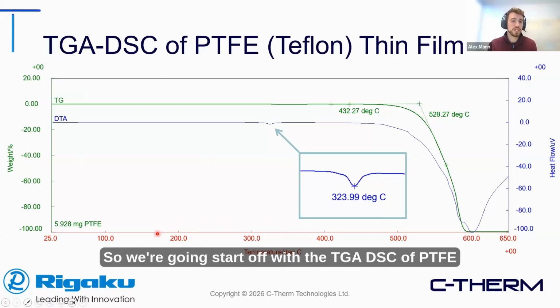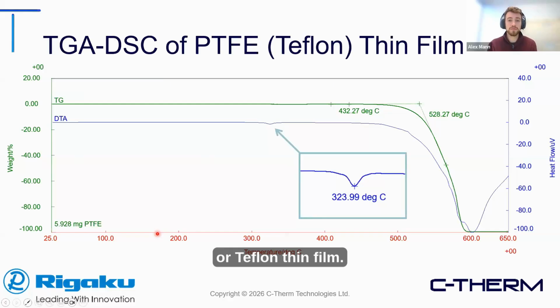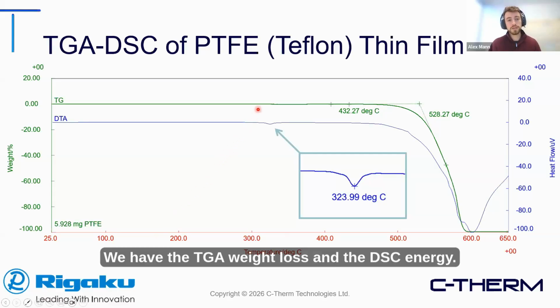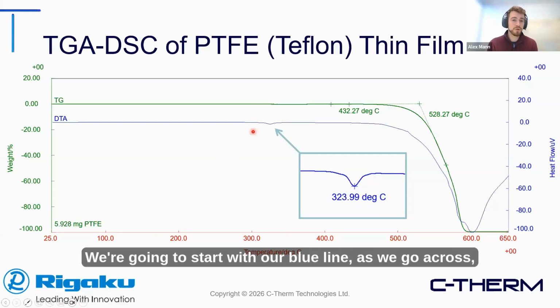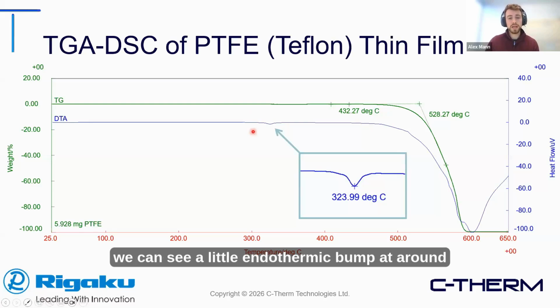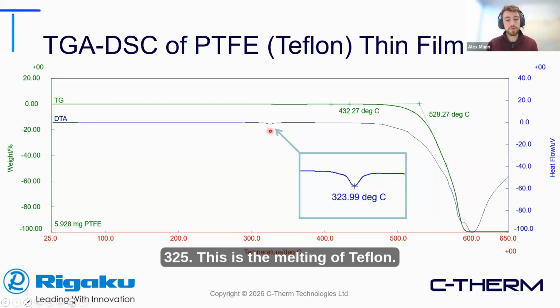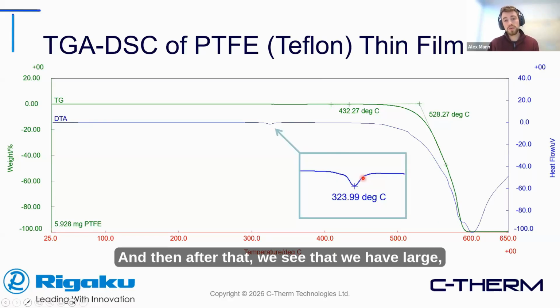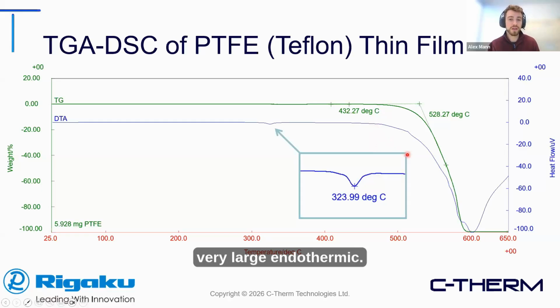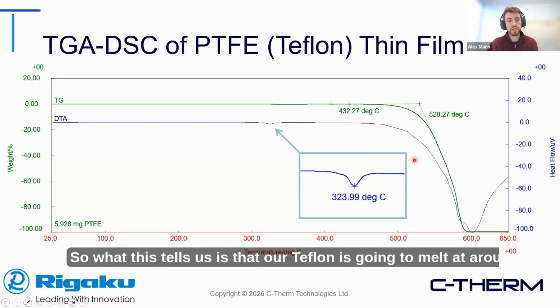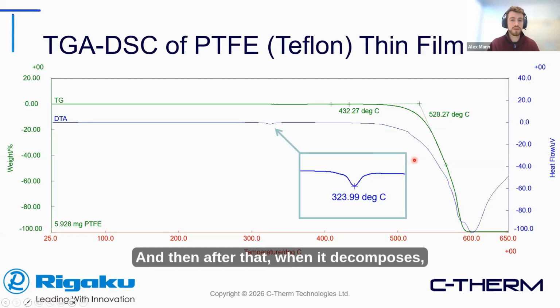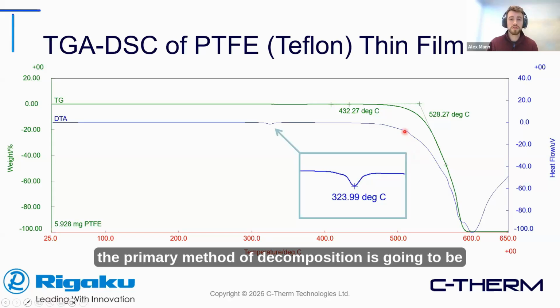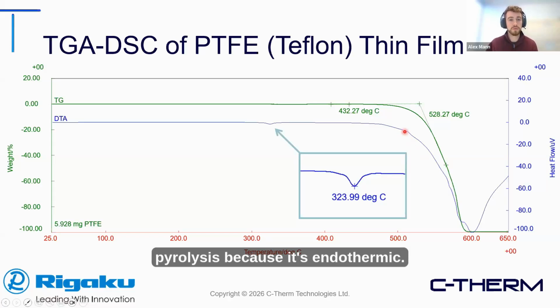So we're going to start off with the TGA DSC of PTFE, or Teflon thin film. So we have two things going on here. We have the TGA weight loss and the DSC energy. We're going to start with our blue line. As we go across, we can see a little endothermic bump at around 325. This is the melting of Teflon. And then after that, we see that we have a very large endothermic. So what this tells us is that our Teflon is going to melt at around 325. And then after that, when it decomposes, the primary method of decomposition is going to be pyrolysis because it's endothermic.